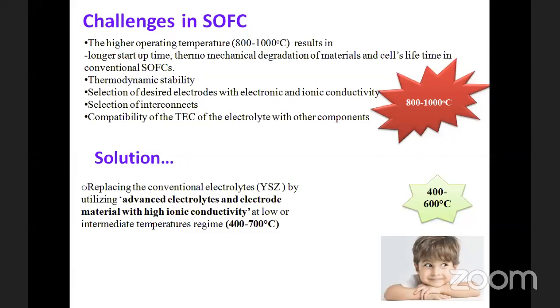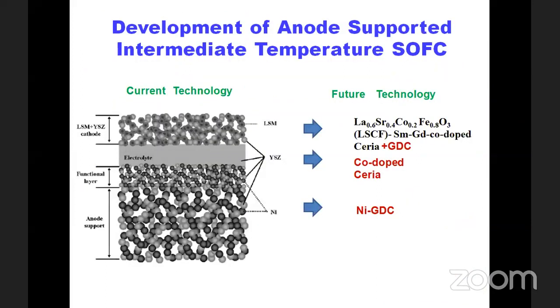But you have to connect it and make it like a device. Therefore, all the joining components, everything should have excellent compatibility in terms of the thermal expansion coefficient. Therefore, people were thinking very deeply about what to do. They were thinking, why not replace the conventional electrolytes like zirconia with advanced electrolytes and electrode materials with high ionic conductivity, which at the same time can be operated at intermediate temperatures ranging from 400 to 700 degrees Celsius. So therefore, we tried to develop such novel materials in our center.